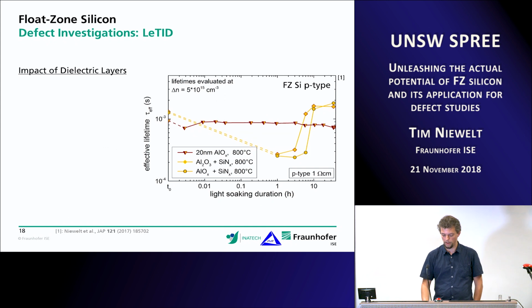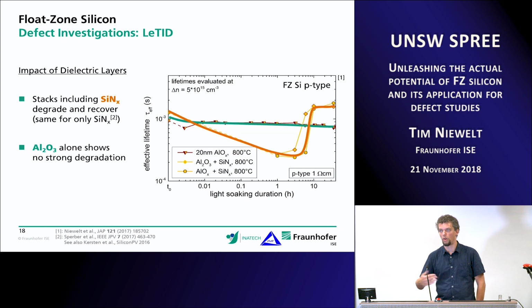Okay, let's look at the impact of the dielectric layers then. So what we see is that, yes, the silicon nitride layer, also on float zone silicon, we do need a silicon nitride layer in order to have this degradation. Here you see the comparison of samples where this one sample just had an aluminum oxide passivation layer and was fired with that, and it's not really showing any degradation or relevant degradation, while the sister samples fired at the same temperature show quite strong degradation. Yes, so all passivation stacks, including silicon nitride, show the typical behavior of degradation and recovery.